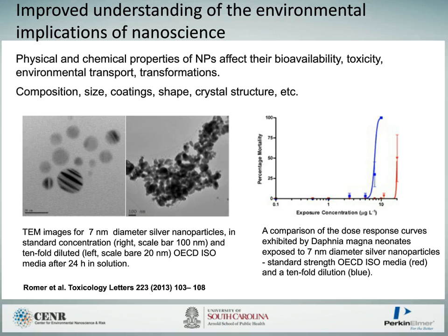And on the right, we have the outcome of that. We have a dose-response relationship with mortality of the Daphnia on the y-axis and the exposure concentration on the x-axis. And the blue line is the diluted material. So the media is diluted, and the particles are individual dispersed particles. And what you see there is a relatively toxic material with an LC50 of a few micrograms per liter. LC50 is the lethal concentration for 50% of the population.